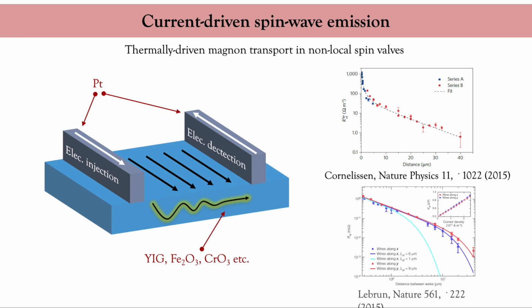A similar work has been recently achieved by the group of Mathias Kläui in Mainz, but this time considering an insulating antiferromagnet. Again, they obtain a very large magnon spin relaxation length that far exceeds the electronic spin relaxation length in light metals. These experiments tell you that magnons are excellent information carriers, in fact much better than electrons, as they can propagate over distances exceeding 10 microns.